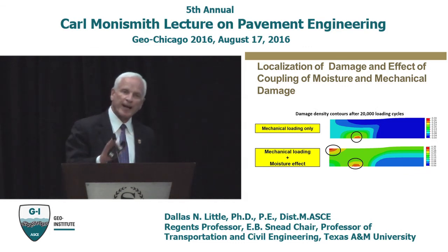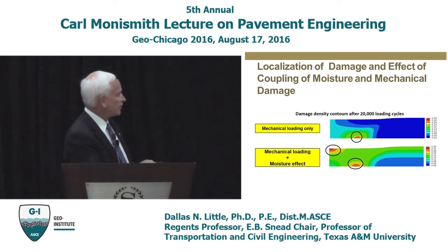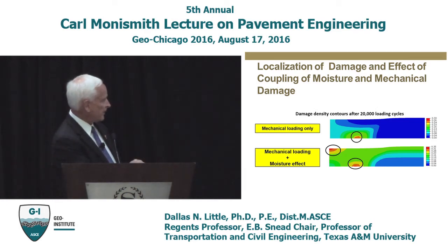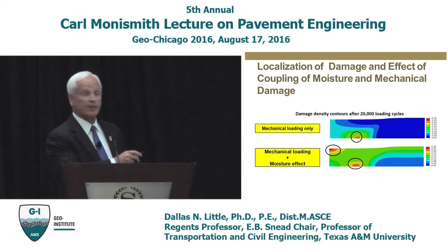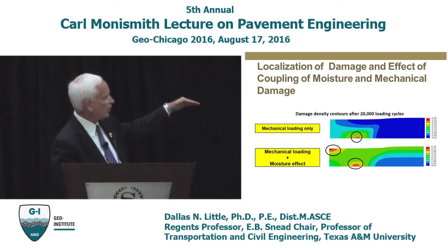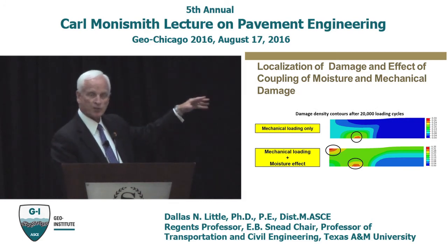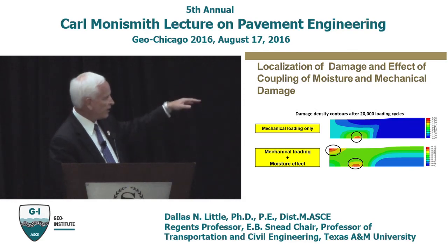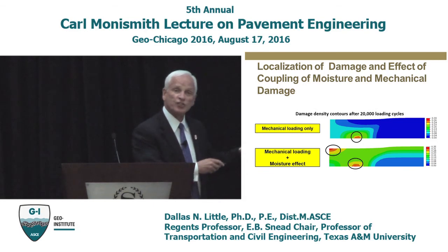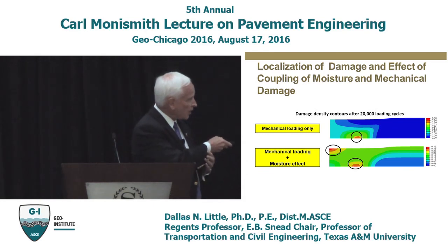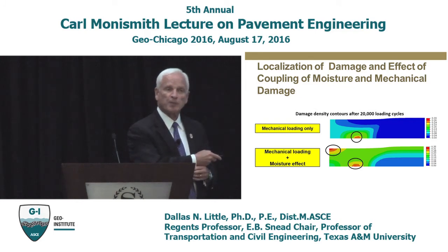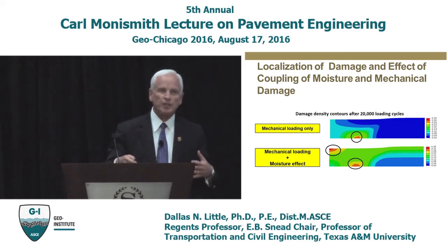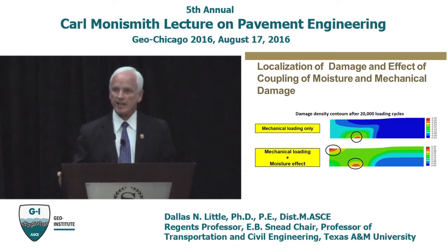Let's now look at some practical application of all that. So here what I have in these particular rectangular plots is the asphalt layer. And these are contours of damage. On the top, you've got mechanical loading only after 20,000 cycles. So the asphalt's been subjected to 20,000 cycles. Notice where the localization of damage is. Damage localizes down here in the red, which is at the bottom of the asphalt layer, near the edge of the tire load. That's not a big surprise. Intuitively, we kind of figure that that's what's going to happen from layered elastic analysis.